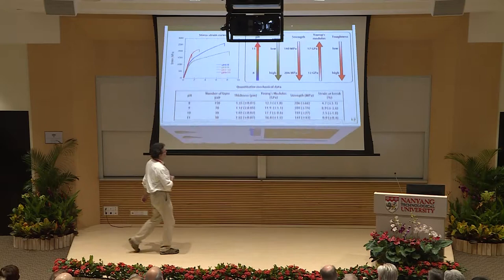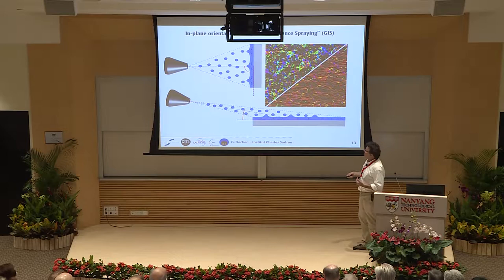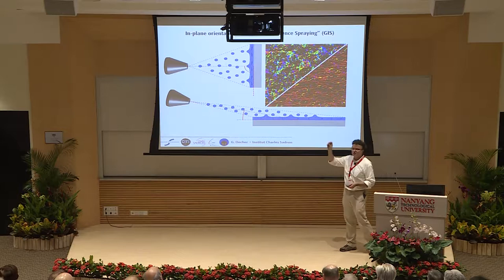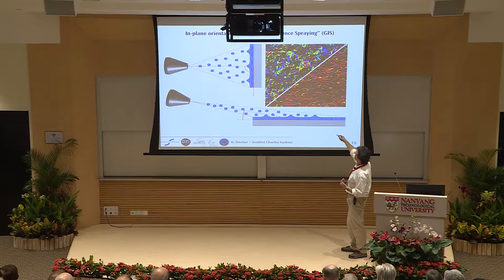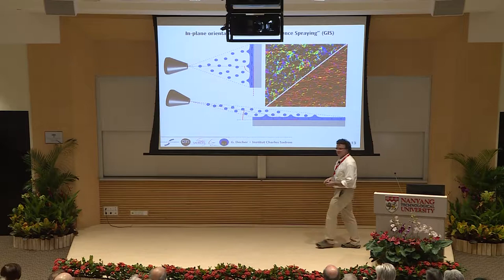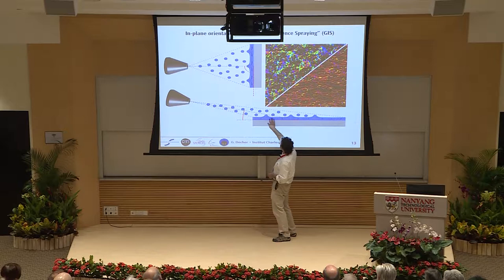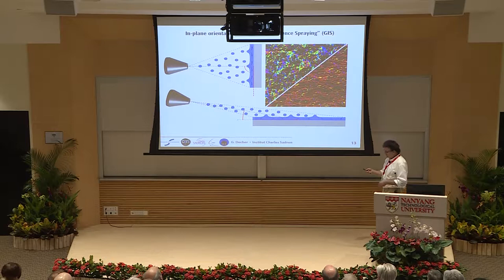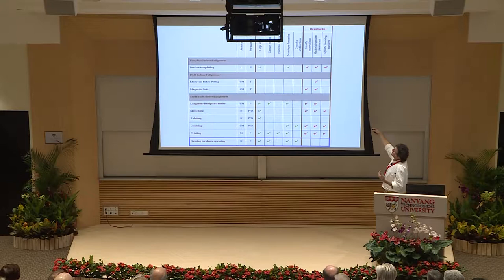We can try to make materials anisotropic. Instead of spraying orthogonally against the receiving surface — which gives a disordered film where color represents orientation direction — we spray at a grazing angle. Shear causes surface flow, and the surface flow orients the fibers. This is a comparison of different alignment techniques: most require heavy equipment or magnetic fields, work only on small areas.